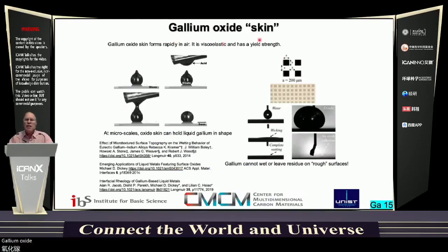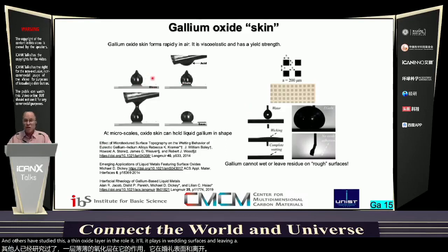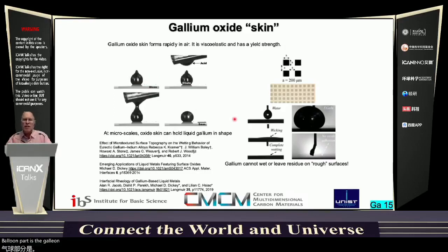gallium oxide skin that's only maybe 1 to 2 nanometers thick, Ga2O3. And others have studied this thin oxide layer and the role it plays in wetting surfaces and leaving a residue, for example. And we could think of it a little bit like a balloon full of water, and the balloon part is the gallium oxide containing the liquid gallium.